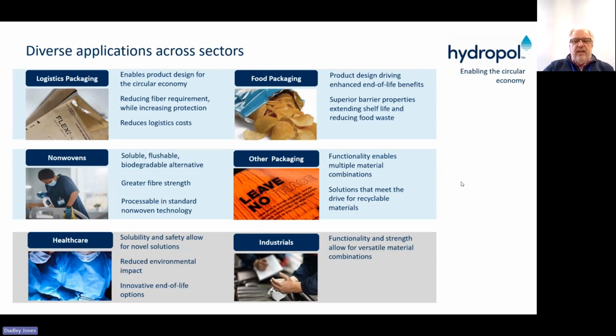Where do we see our product being used currently? We've seen it being used in mailer bags. People use it in combination with paper laminated to Hydropol film for mailer bags. You can reduce your thickness of paper and you get improved puncture resistance and strength, which I'll show you the features of in a minute. In non-wovens, I've spoken to you about, they would be wipes or sheets that can be solubilized. In healthcare, it's bags to stop contamination of used clothes, specifically during COVID, where people didn't want any contact. They just put the clothes into the bags and the bags into the washing machines.